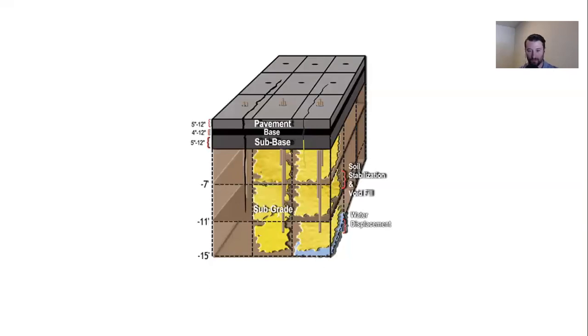And because we were going so deep and building that skin friction, instead of drilling individual holes, we drilled single holes and dropped a cluster of 5, 10, 15, 20, 25, 5 plus tubes. I think we actually added more than 5 just in case tubes got clogged. But we dropped all of those tubes to depth at once, and then came back and did our injection.